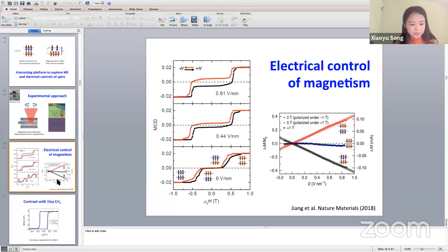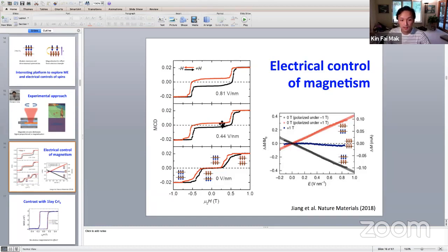Okay, thank you. So I think one question about the first part of your talk is from Tyler. Is it actually possible to induce some magnetization of the sample using gate voltage with no magnetic field? Yeah, actually, this is what's been shown here, right? The red curve and the black curve here are the induced magnetization perfectly under zero magnetic field. With large enough electric field, you can generate quite substantial magnetization, like 25% of the saturated magnetization. So you can generate quite substantial magnetization in the system by a simple electric field, under perfect zero magnetic field.